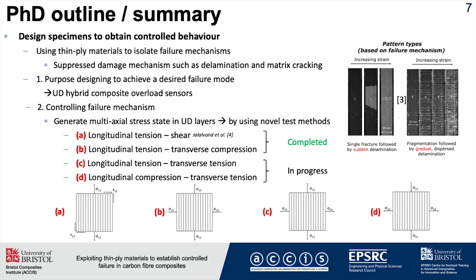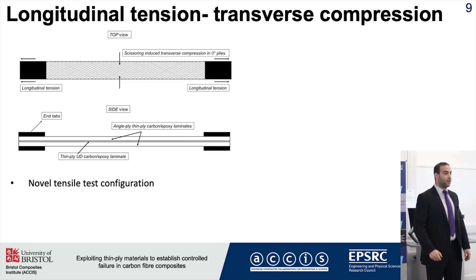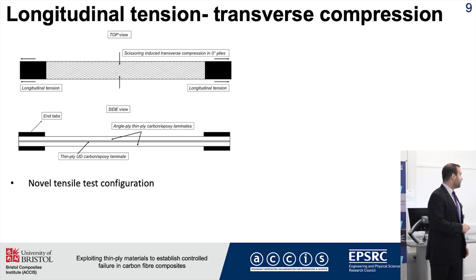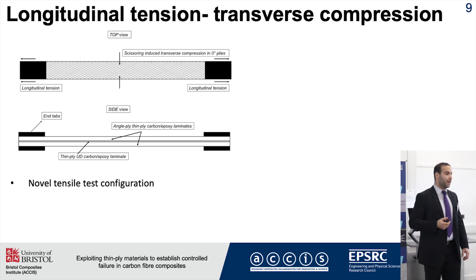The other project is to control the failure mechanism by generating multi-axial stress states in the unidirectional layers using novel test methods. I've been working on four different loading cases — two of which have been completed to date, and two which I'm currently working on. I will now talk specifically about the longitudinal tension and transverse compression case, where we developed a novel tensile test configuration with thin ply UD carbon epoxy laminates in the center, embedded in angle ply thin ply blocks of the same material, and the transverse compression is applied to the central UD layers by the scissoring deformation of the angle ply blocks.